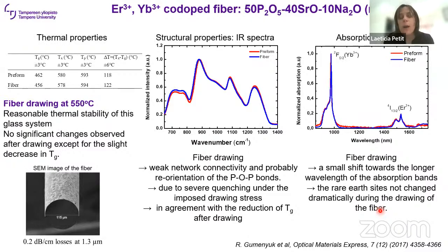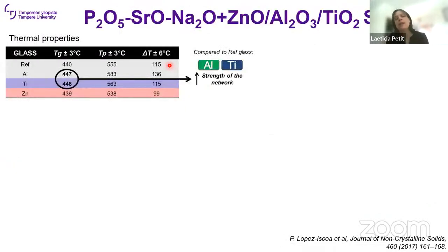However, when we spoke with our partners in the Faculty of Medicine, they want to have as little as possible of the rare earth content. And ytterbium is in a quite high concentration, so they asked us to actually work on the glass composition to reduce the rare earth amount. So what we did, we went to erbium doped with a low amount of erbium, and then we tried to increase the spectroscopic property of the glass by adding zinc, aluminum, or titanium.